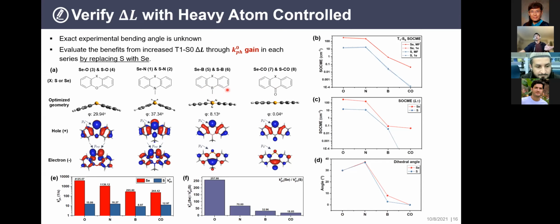So for instance, you know that nitrogen is preferred to have a sp3 hybridization in this type of material. And that's the reason why this molecule is bending. When you switch to boron, which prefers to have sp2 hybridization, you would expect this molecule to be much more planarized, which actually has a much smaller dihedral angle of 8 degrees. And when you switch to carbonyl, which should be much more planarized, right? So actually from the expectation, we have a dihedral angle of around 0 degree, right?